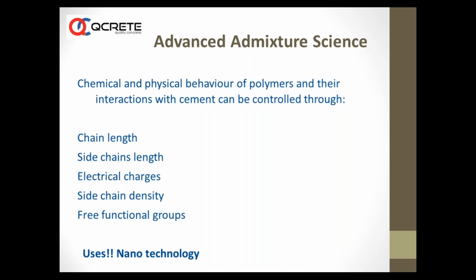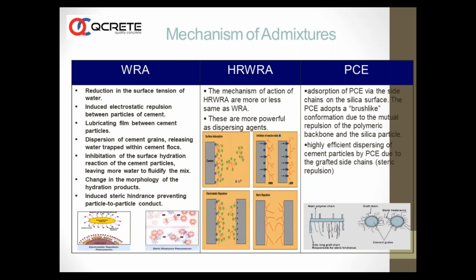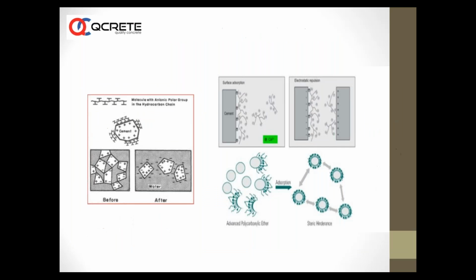Now the mechanisms, in short, are almost similar, but PC admixture operates on steric hindrance, where at a molecular level the deposits of chemical charges give tremendous repulsion, and there is a suspension. These cement particles are suspended for a longer time, and you get high plasticity - high fluidity, longer retention times. Mixes like SCC and things like that are possible using PC based admixture. Another picture of the same.